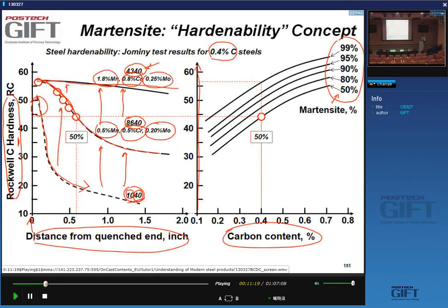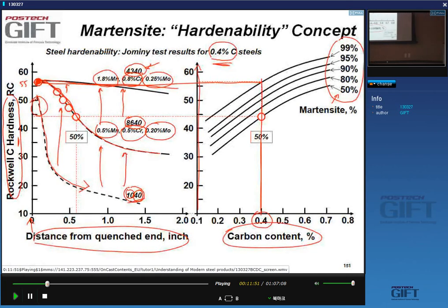All right, so what does this graph tell me? The graph tells me that if, at the very end of my Jominy specimen, I have a hardness a little bit in excess of 55 Rockwell C, I bring this over here and I see where it crosses my vertical line with the 0.4% of carbon, the carbon content of my steel. I see that this hardness corresponds to 99% of